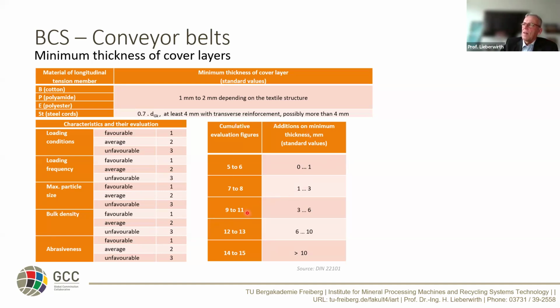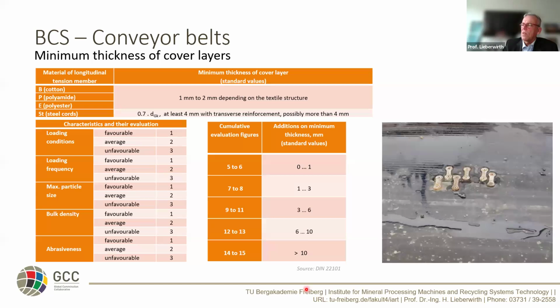And we can add this up, and then we can derive a certain number of millimeters for the surface. If you don't do it, your belt would look like this one. This is a belt feeder here, the one which was started and stopped frequently. It had originally 32 millimeters of rubber covering the core rubber. So not even just the steel core. On top of the core rubber, we had 32 millimeters of rubber. And you can see that rubber was eaten off completely. And even, of course, then the belt is damaged quite quickly. And so it was repaired here, but this is not a long-lasting solution.